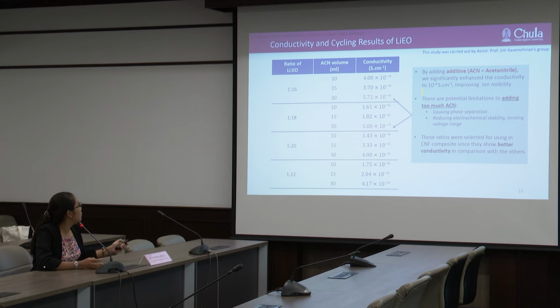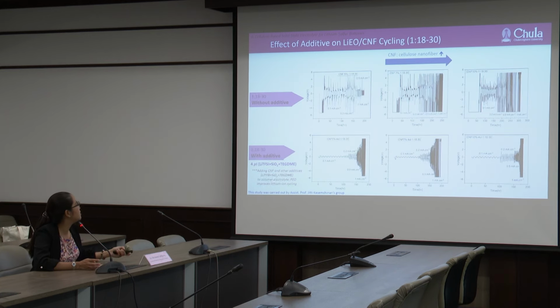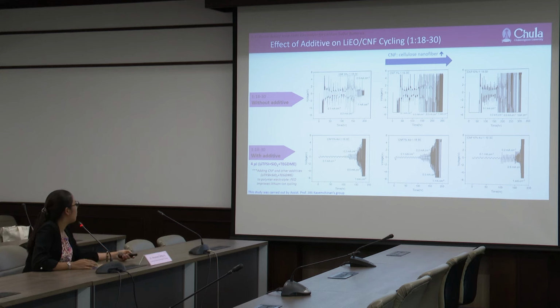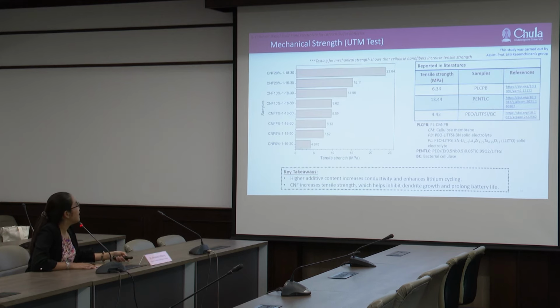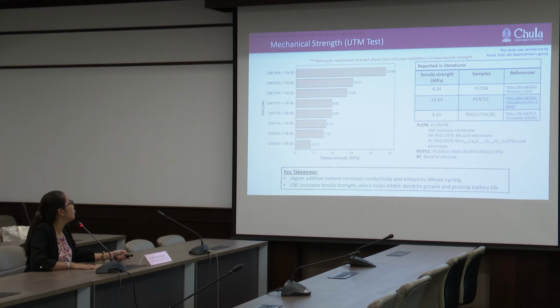From the results, we pick the ratios of lithium to EO at 1 per 16 and 1 per 18 at 30 milliliters of acetonitrile for use in the cellulose nanofiber composite, as they show the better conductivity. We found that by adding cellulose nanofiber and other additives to PEO, we can improve the lithium-ion cycling, from the result here. In addition, testing mechanical strength via UTM test, the results show that cellulose nanofiber increases tensile strength.